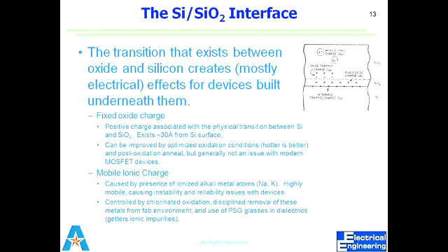So this is the silicon surface, this is silicon dioxide, and that fixed oxide is always very close to the silicon surface, not more than 40 angstroms away from that. And this is named QF. We call it QF, that is fixed oxide charge.